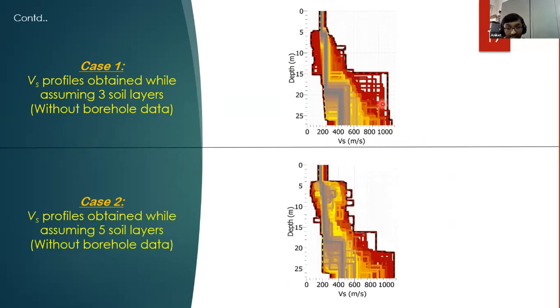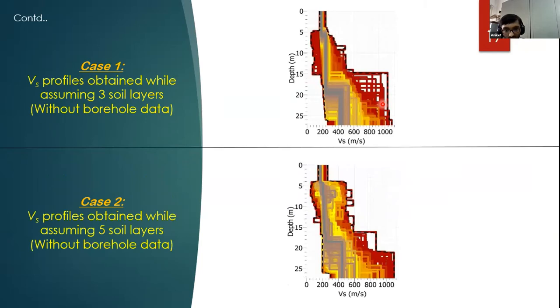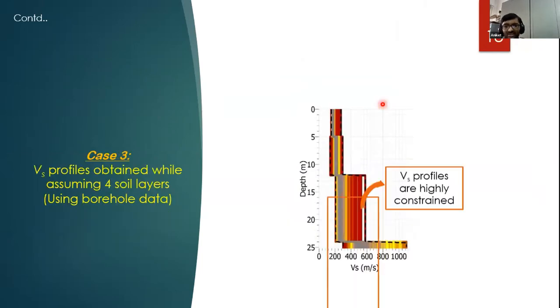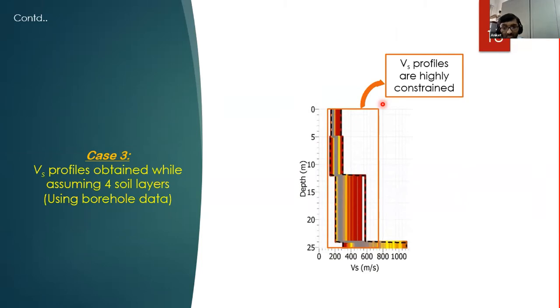In case 1, we can see that there are a number of VS profiles, and even at a single depth, the value of VS for different profiles ranges from a very small value to quite a high value. In case 2, again, the same thing is visible. The data scatter is quite high. But when we see the case 3 results compared to case 1 and case 2, in case 3, the VS profiles are very much confined to a narrow band and the uncertainty is reduced.